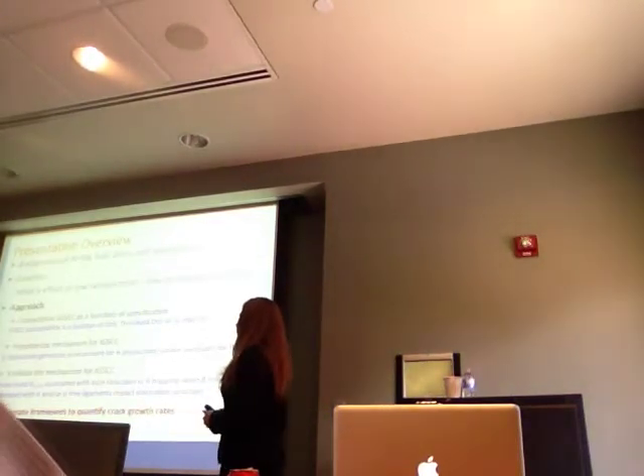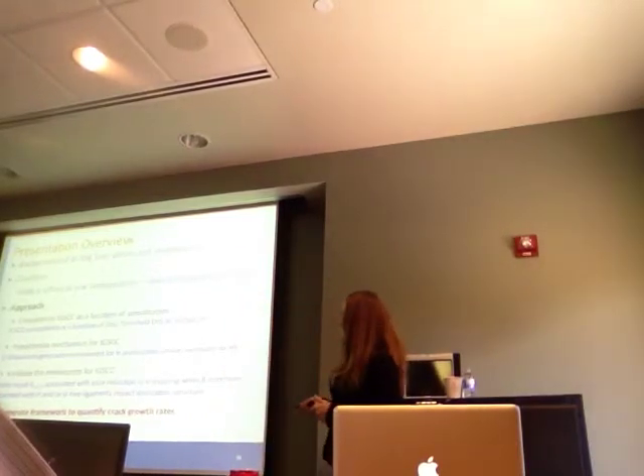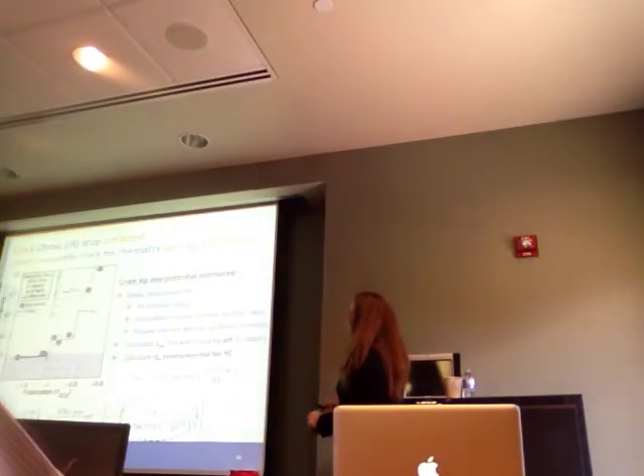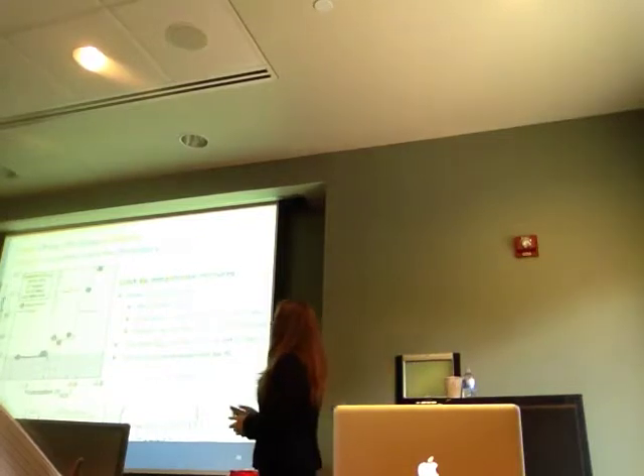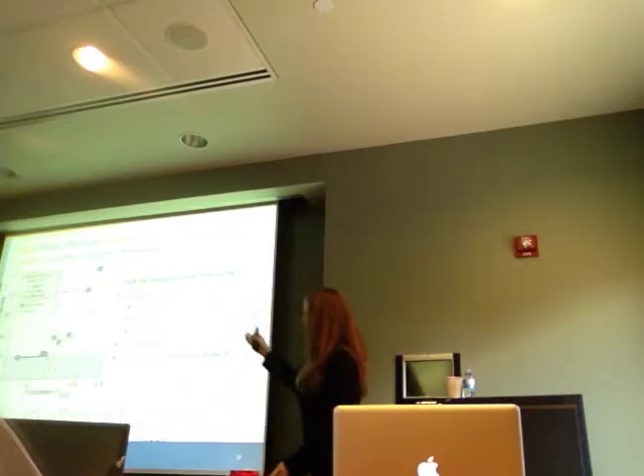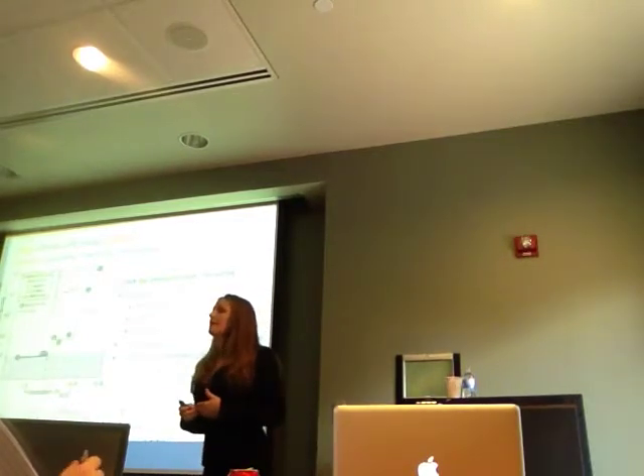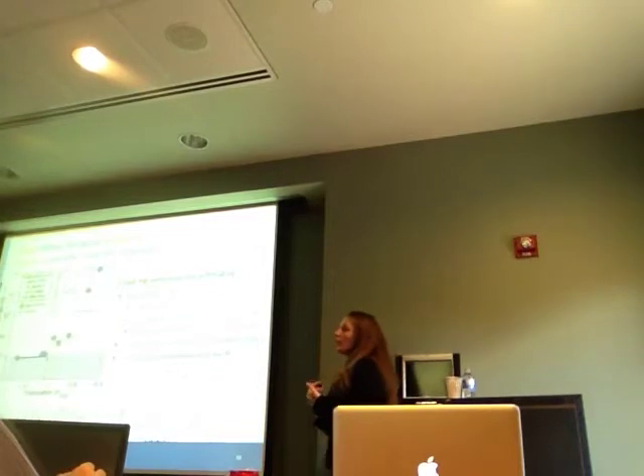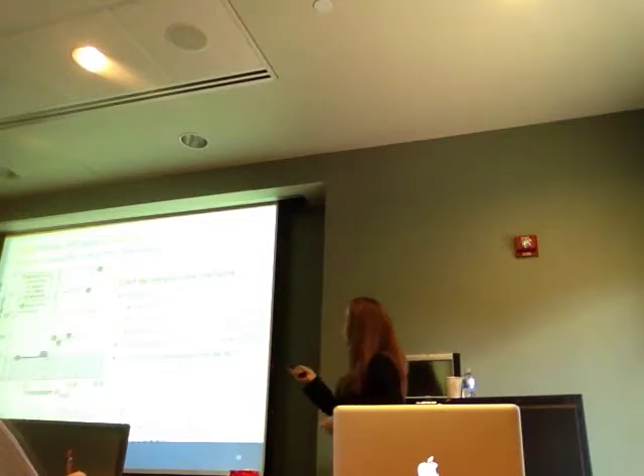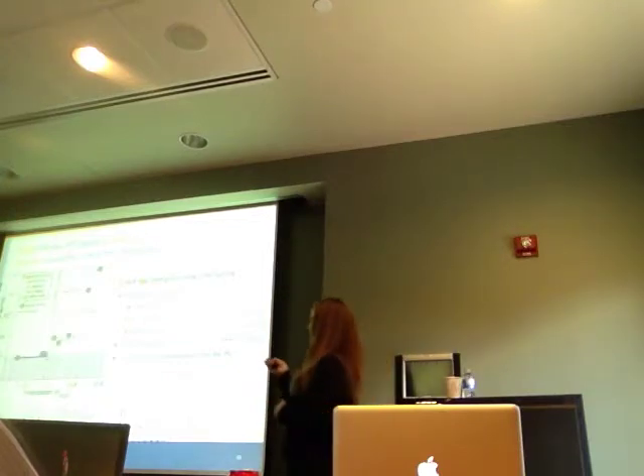All right, well that brings us to our last section, and that's how we can generate a framework to quantify crack growth rates. So Professor Kelly helped me predict the ohmic drop at the crack tip for all of the experiments that I ran in this work. And we did this by first establishing a pit stability criterion. Basically, your pit will grow if you have a combination of current and diffusion distance high enough or above your pit stability criterion.